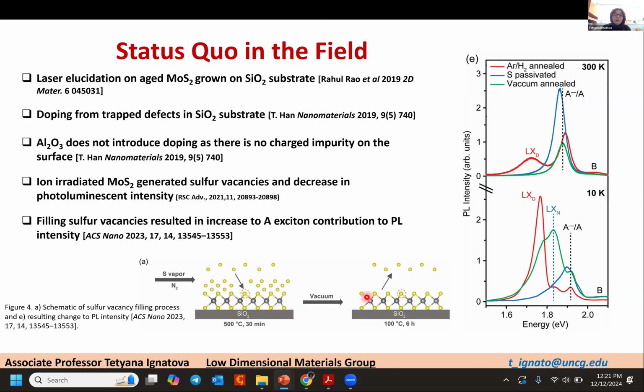We also found an interesting paper where photodoping was combined with introduction of sulfur vapor, and people saw significant changes in photoluminescence, and they attributed these changes to rejuvenation of sulfur defects in the presence of sulfur vapor. You can see here the results from the paper. Okay,